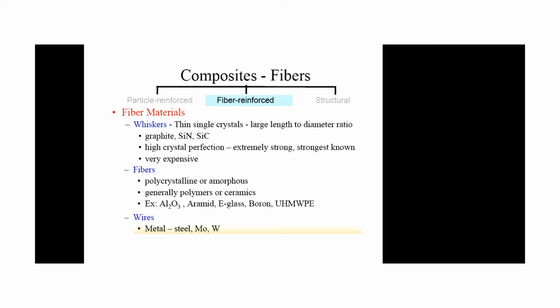So people have made the whiskers, meaning single crystal fiber of many of the ceramic material like silicon carbide, alumina. So if they added into the composite, then strength will be much higher as compared to conventional fiber. Why? Because they are very strong and they have a very low defect. But of course, they are very expensive.